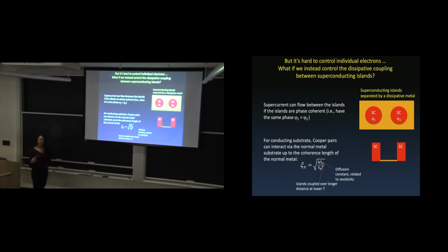So here we have, top view, two islands on a metal, and you see I put them as different phases, because if they're not coupled together, they have different phases. From the side view, it's two superconducting islands on top of a metal. In this case, a supercurrent flows between the islands if the islands are phase coherent, meaning that if they have the same phase, you get a supercurrent flowing. If they don't have the same phase, you don't get a supercurrent. So how do they get the same phase if they're on a metal? The metal has to be phase coherent itself. So these two islands are phase coherent up to a distance where the metal between them is phase coherent, and that distance is given by the normal metal phase coherence length, which is related to the resistance of the metal and inversely related to the temperature.